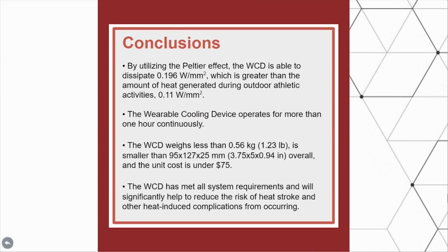The wearable cooling device is able to dissipate 0.196 watts per square millimeter. This is greater than the average amount of heat generated during outdoor athletic activities, which is 0.11 watts per square millimeter. It operates for more than 1 hour continuously, weighs less than 0.56 kilograms, it's smaller than 95 by 127 by 25 millimeters, and the unit cost is under $75. It has met all of the system requirements, and it will significantly help to reduce the risk of heat stroke and other heat-induced complications from occurring.